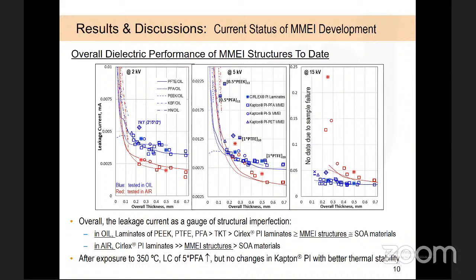As I mentioned earlier, we also monitored the leakage current. Overall, the SOA single-layer materials showed the lowest LC either in oil or air. Then MMEI next, much lower than that of Cirlex, particularly in air. In addition, as a proof of the concept, LC of PFA increased considerably after exposure to 350 degrees C, but no changes for the Kapton PI, which had much better thermal stability.